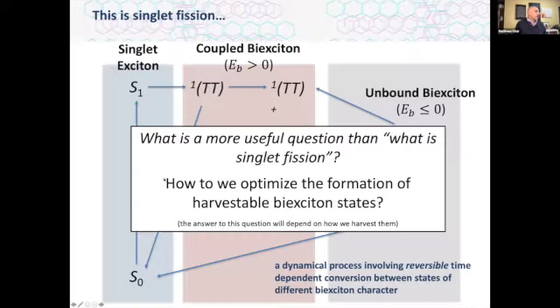Yeah. So the energy differences are on the micro eV scale. If we're talking about the triplet pair and the quintet triplet pair, they're micro electron volts. They're tiny. But yet they stay polarized. In the ESR language, I had to learn this because I'm an optics person, so polarization means the orientation of the electric field vector. And in electron spin resonance, it means you're in a sublevel preferentially. So again, we have these quintet, triplet, singlet sublevels. If you have more population in one than the other, in spin resonance, that's a polarization. So these states stay polarized, even though we have thermal scales much bigger than the energy splitting.